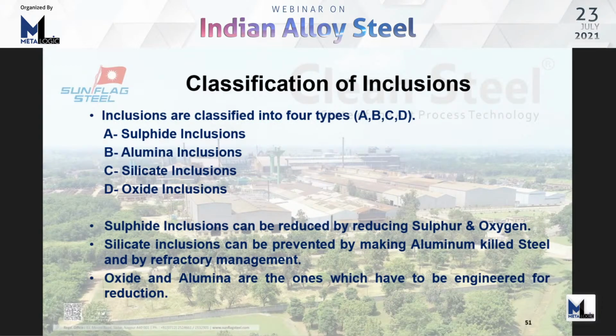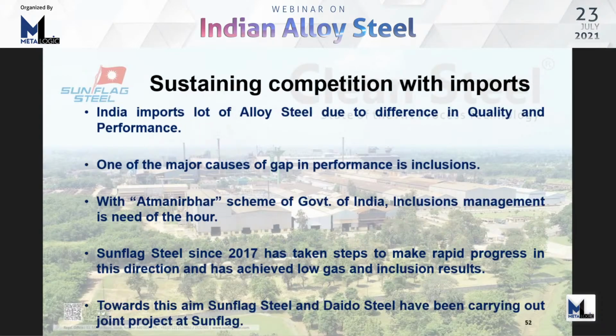Inclusions are classified as A, sulfide type, B, alumina type, C, silicate type, D, oxide type. It is the oxide or alumina which are the ones which have to be engineered, as sulfide can be brought down by control on sulfur and oxygen, and silicate can be brought down by making aluminum killed steels. India imports a lot of alloy steels due to difference in quality and performance. One of the major causes of gap is the inclusions. With Atmanirbhar scheme of the government, inclusion management has become need of the hour.